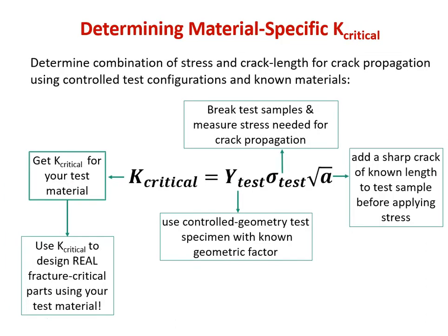So speaking of testing, how the heck do you get these K values and how do they relate to a material? I mean, so far we've only looked at crack length and applied load and geometry. Isn't this a materials class? Well, absolutely. If we do several tests and we establish K for a variety of crack lengths and a variety of loads, all with the same Y, we will end up with something that is indeed specific to the material. And that's what we call K-critical. And that is a material-specific property, just like elastic modulus, Poisson's ratio, yield stress, ultimate tensile strength, whatever. So that's where we start to get material-specific.